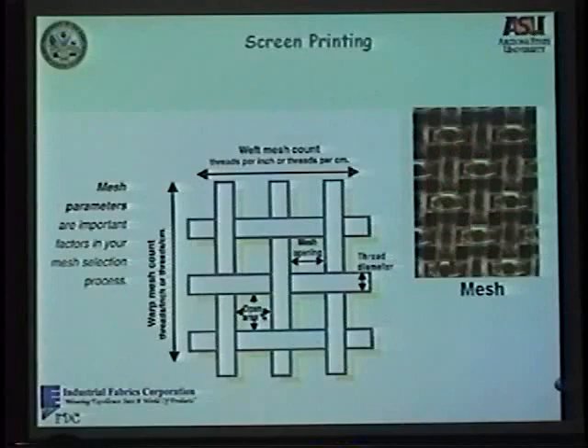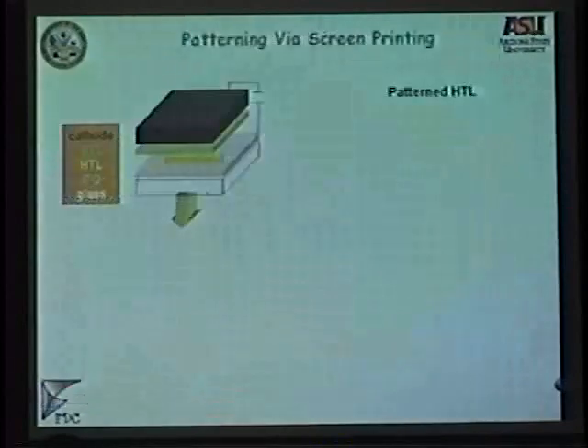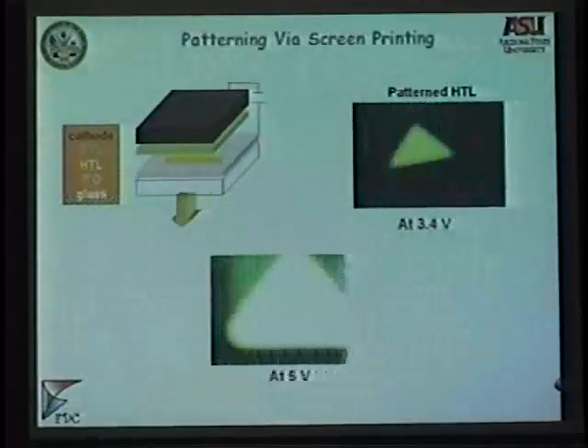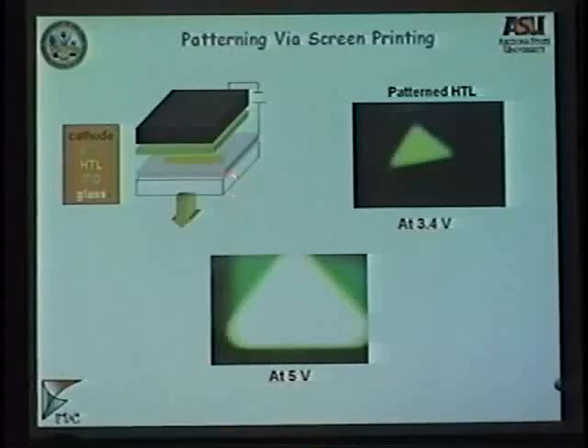So there's a lot of engineering and art that goes into this, but let me show you what we did quickly. We printed a triangle, about 1 inch in height. We printed it with screen printing, and on top we deposited ALQ all over, to see if the screen printing is really giving us patterning or not. If it's not, you should see color coming out from all this rectangle here. However, the color comes only from the triangle that we printed.